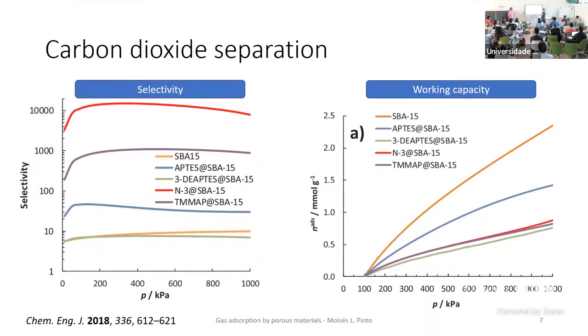But we can, from this raw data, let's call it, calculate selectivity of the separation of carbon dioxide from methane. And you see here that we have several orders of magnitude when we have different composition at the surface. So if we have solids with different compositions, we can tune the interaction of the gases with the surface. So you are in the context of a course where probably each one of you has in mind different types of pores and porosity and materials and so on. But just to give this broad spectrum that you can tune the surface of the material to increase selectively the interactions for some of the gases.